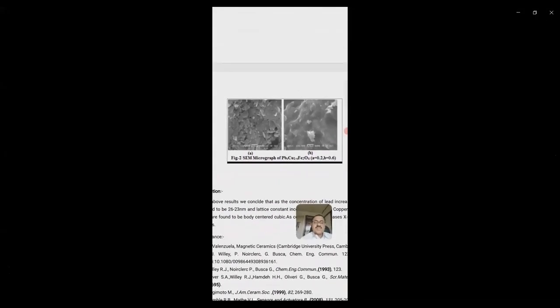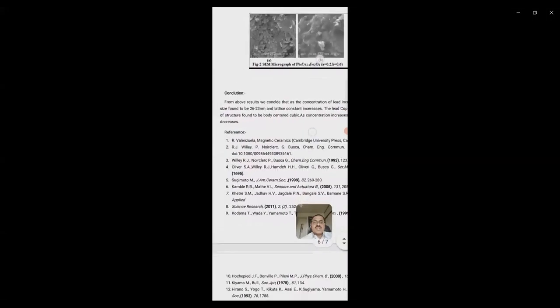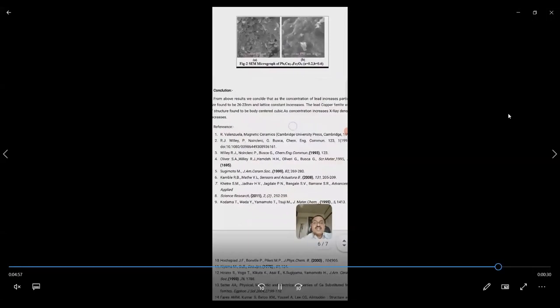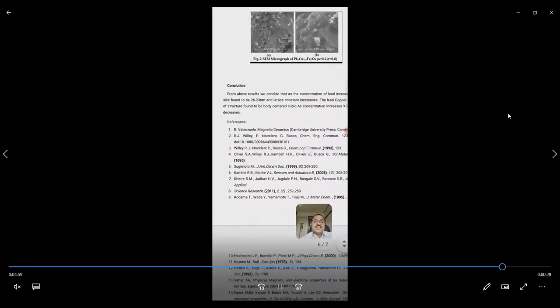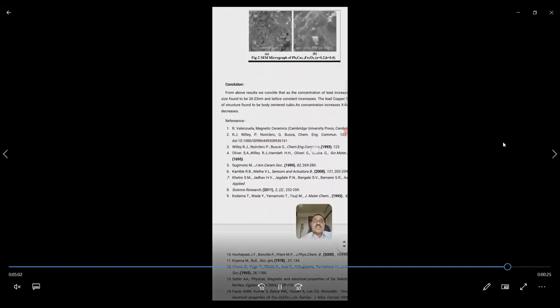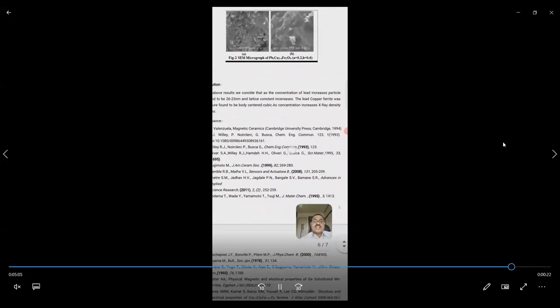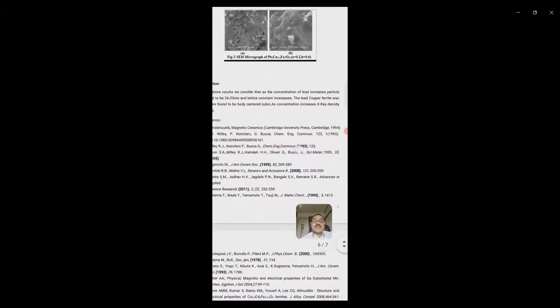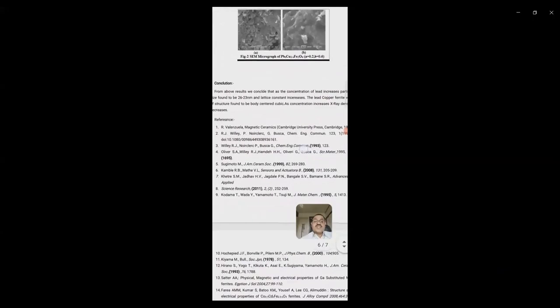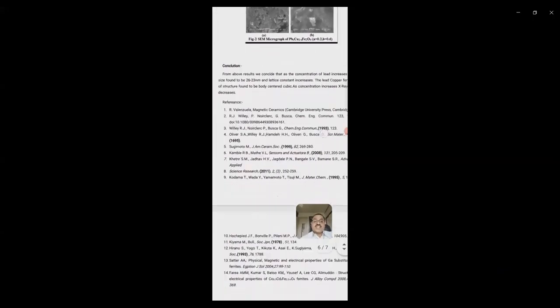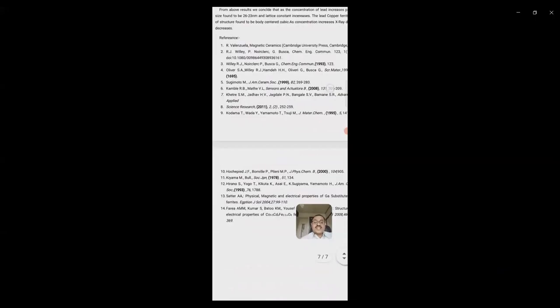These are the SEM micrographs for lead-doped copper ferrite for x equal to 0.2 and x equal to 0.6. From the above parameters, it is observed that as the concentration of lead increases, particle size is found to be 26 to 23 nanometer, and the lattice parameter increases. The lead copper ferrite structure was found to be body-centered cubic, and as concentration increases, X-ray density decreases. So these are the references of my papers. So thank you very much to the organizers.